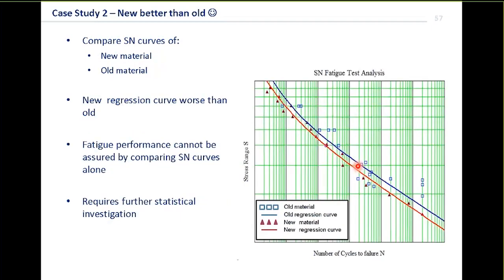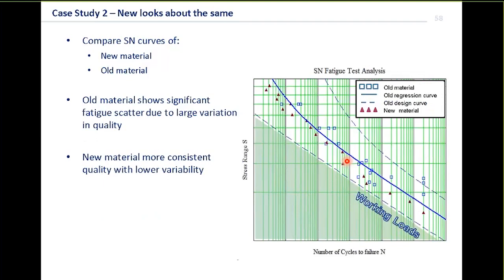However, this is typically what we find. Again, the blue squares are the old material, and this appears to have a better fatigue curve, a better regression line than the new material it's being replaced with. So straight away, we can't really, with any confidence, say that the new material is a suitable replacement. We need to do more fatigue analysis, more statistical analysis.